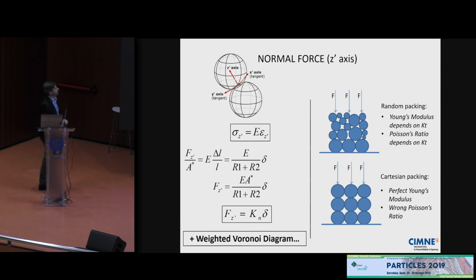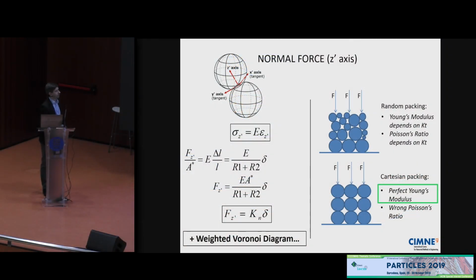Now, if you use this scheme and add the weighted Voronoi diagram to compute the areas, if you use a random packing, you'll still get a wrong Young modulus, because it still depends on KT, and a wrong Poisson's ratio. But if you use a Cartesian packing, that's good news. You get the perfect Young modulus. That's some beginning, and still a wrong Poisson ratio.